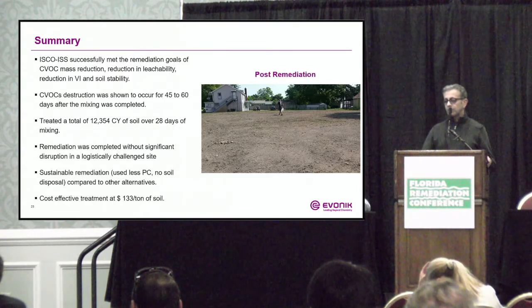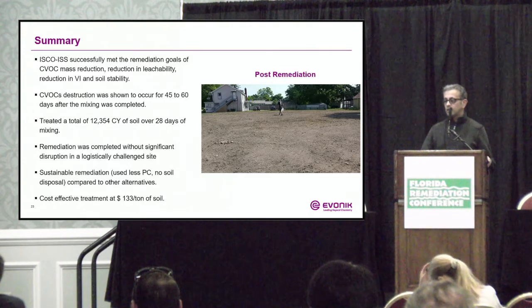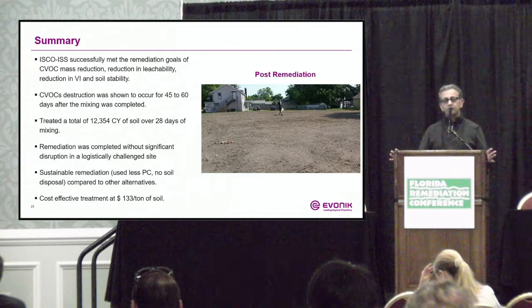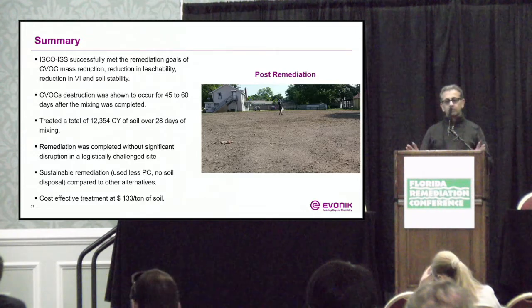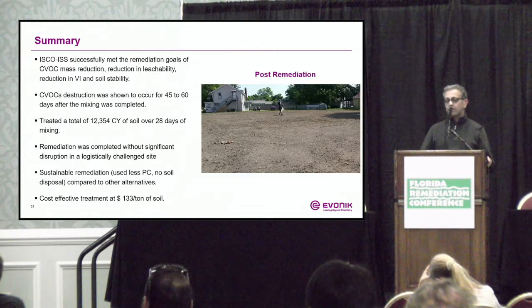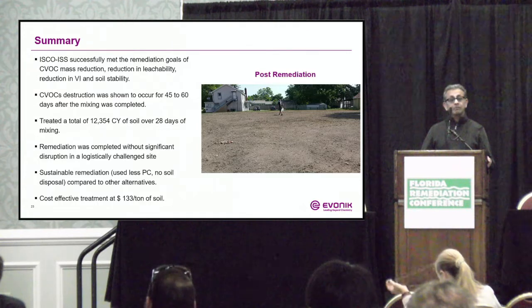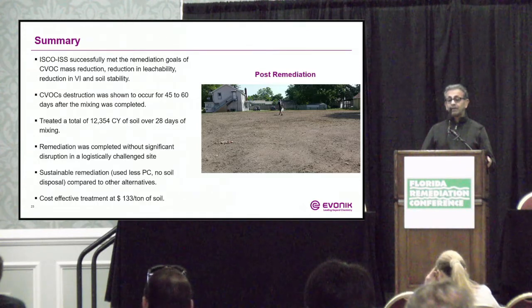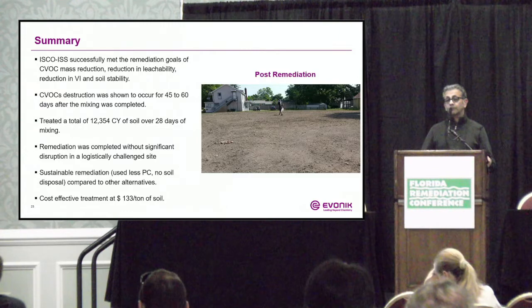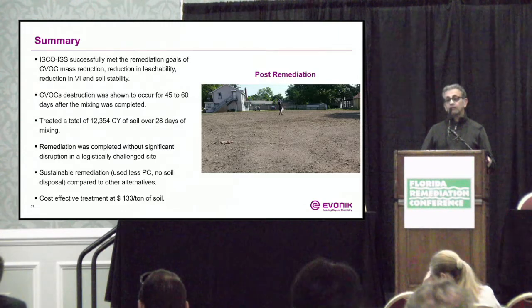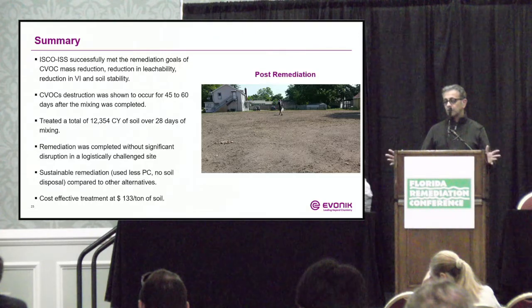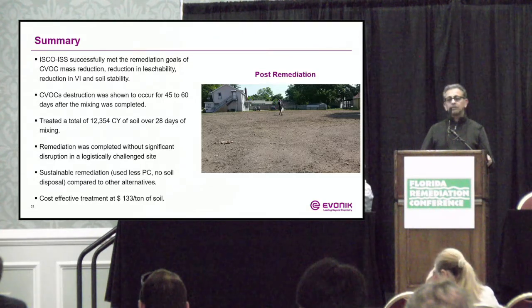Again, we treated about 12,400 cubic yards of soil in 28 days. Remediation was completed without significant disruption to the neighboring community and residences. It was a sustainable remediation because we did not end up excavating and sending soil off-site, and a very small amount of Portland cement was used. And it was a cost-effective treatment at $133 per ton.